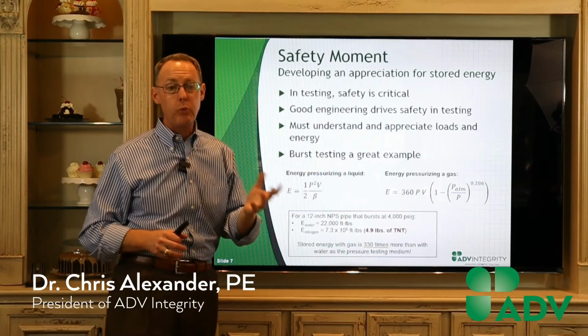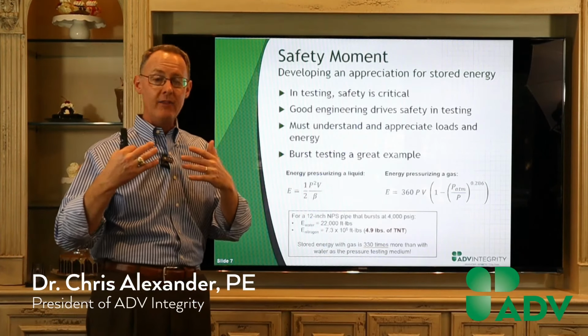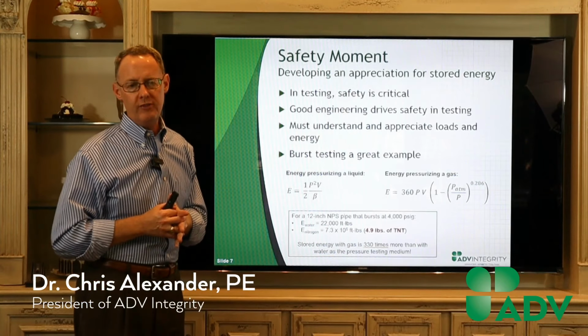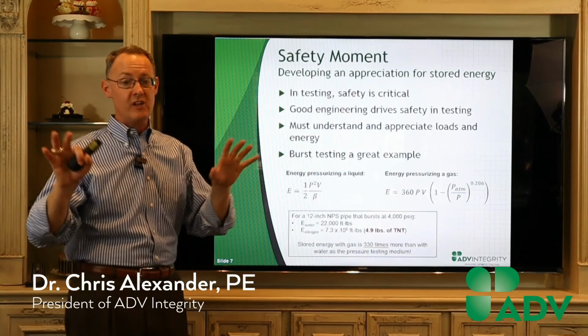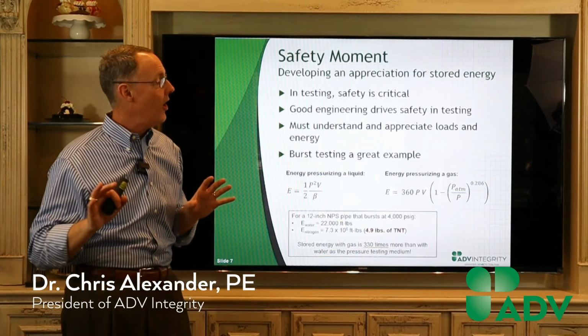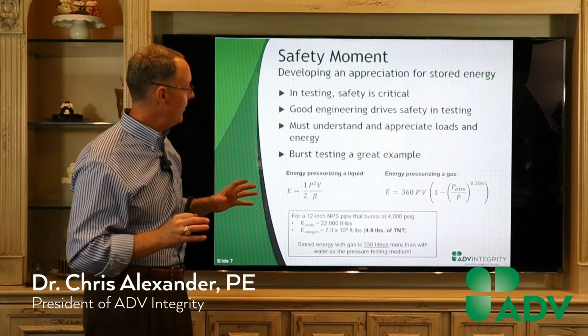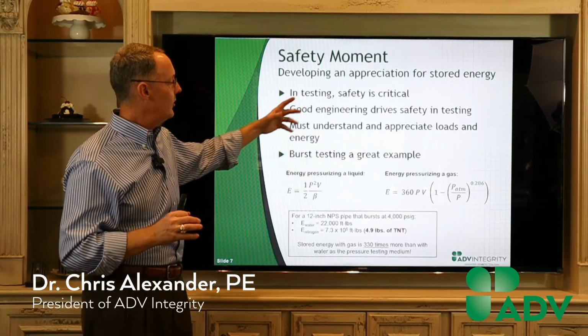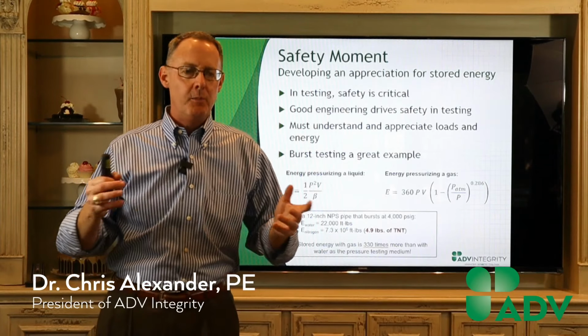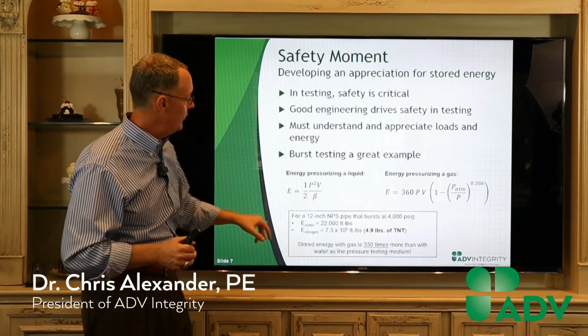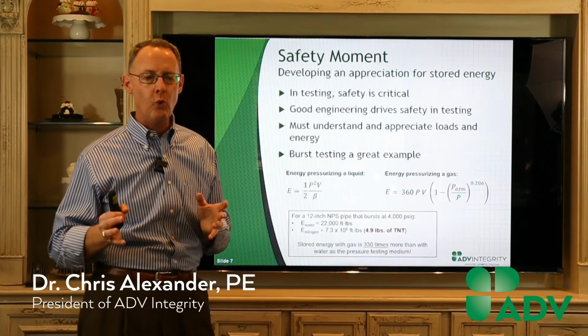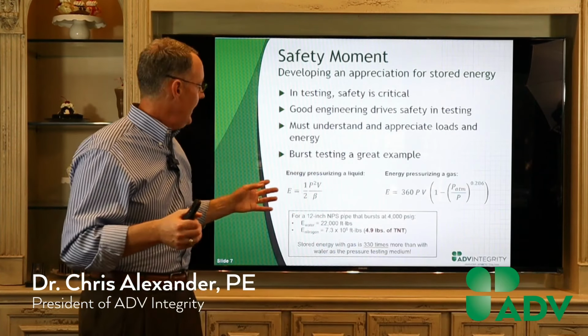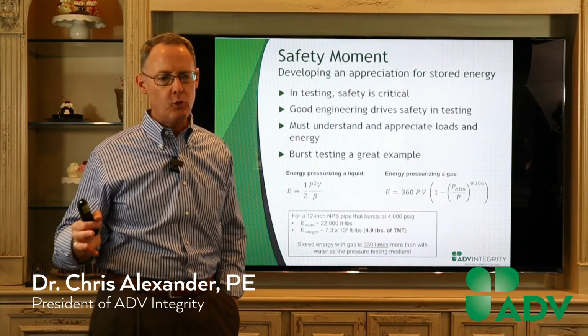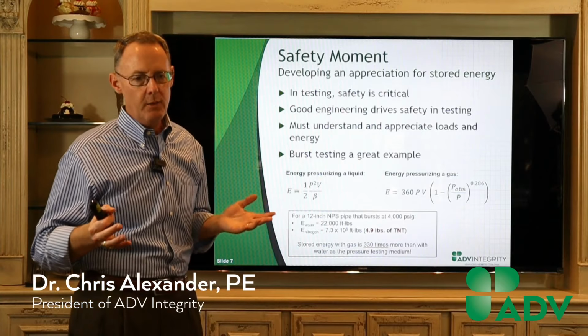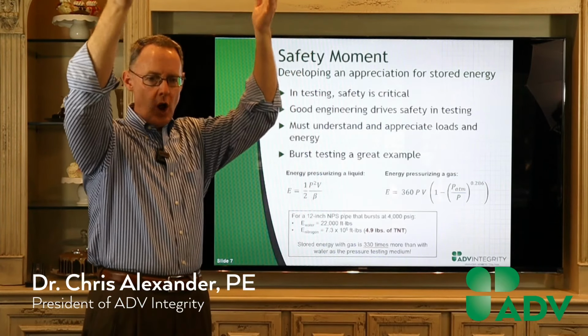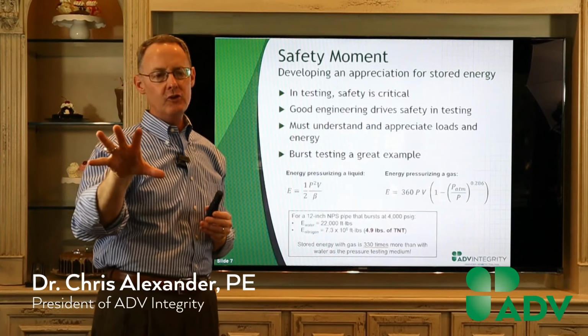It's just 1/2 times the pressure squared times volume divided by the compressibility of water, which is about 330,000 psi. I promise you this is the only slide that has any equations because I don't want to lose the audience. Get a bunch of differential equations and you lose everybody. So this is the energy for water. We do a lot of burst tests on 12-inch pipe. And typically the pipes fill at about 4,000 psi. If you run through that, the amount of energy that's stored in that sample at 4,000 psi is around 20,000 foot-pounds. Specifically, it's 22,000. So if you envision, if I was able to take 1,000 pounds and drop it from 22 feet, that's the kind of energy level we're talking about.